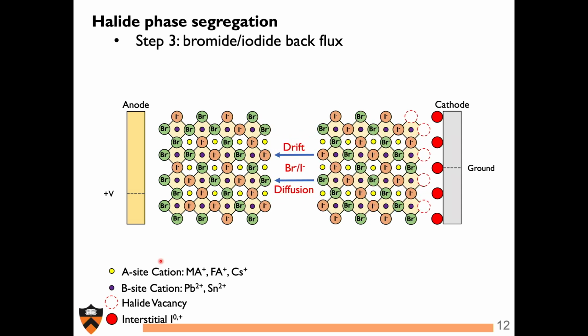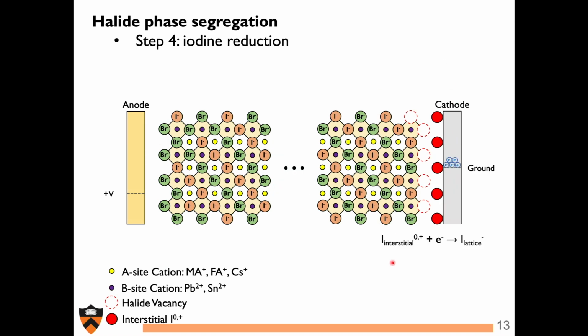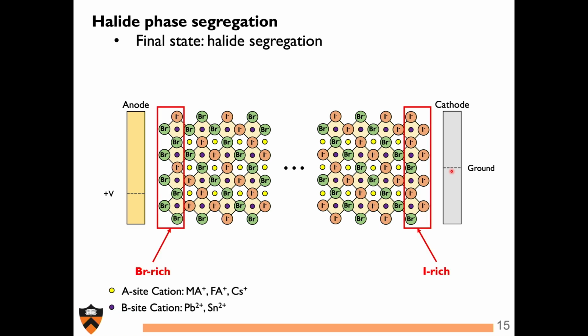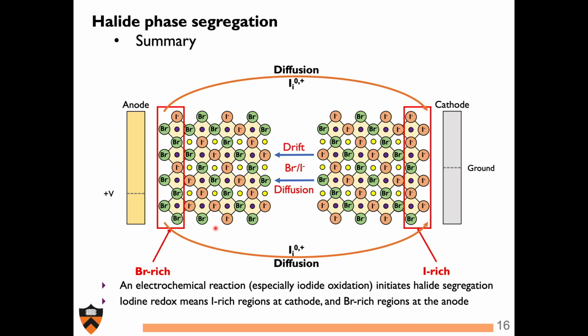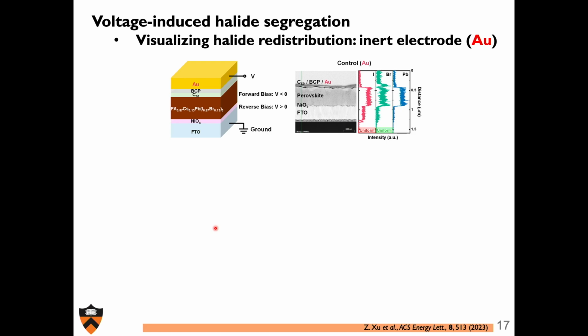And now I have a lot of vacancies that have moved to the right here. And the electrons can re-reduce the iodide. So this is the closed circuiting of this electrochemical cell. They can re-enter the lattice as negatively charged iodide ions. And the net result is I have an iodide-enriched cathode and a bromide-enriched anode. And if I test this experimentally, we can see if this hypothesis is true.